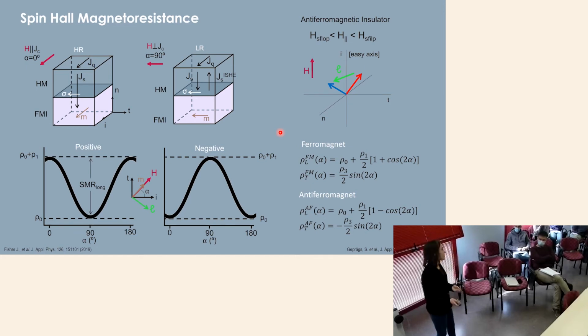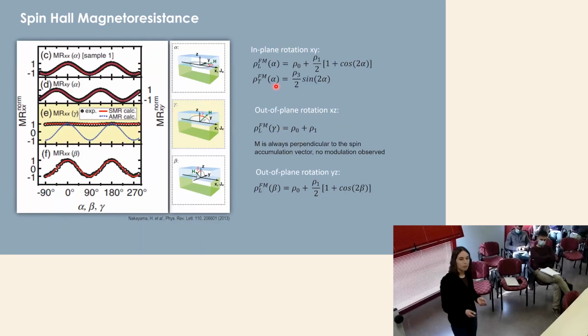So we wanted to try to measure this to figure out the direction of the easy axis and how possible it was to orient it with the magnetic field. And just to give you an example, this can be measured also in different planes. And when we measure in the plane, we will expect to observe a modulation with a 180-degree period. And we can also measure this SMR rotating the field out of plane. And rotating the field out of plane will give different responses depending on which plane we are scanning.